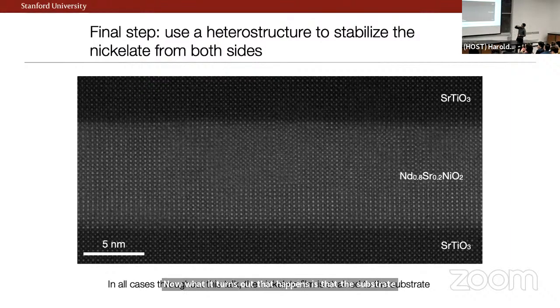Now, what it turns out that happens is that the substrate is very important for essentially being a director. It kind of guides which plane of oxygen to deintercalate. And by breaking this degeneracy, there's a proximity effect where we can stabilize the right phase for a few nanometers. So kind of the ultimate structure that we can grow looks something like this. We have a heterostructure so we can gain these proximity effects on either side.